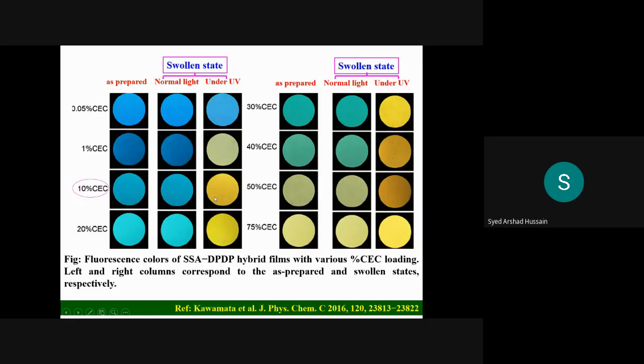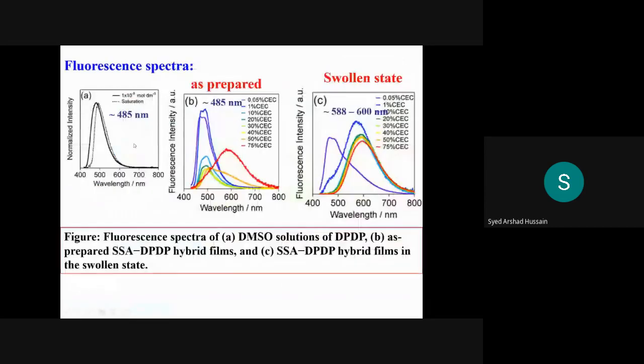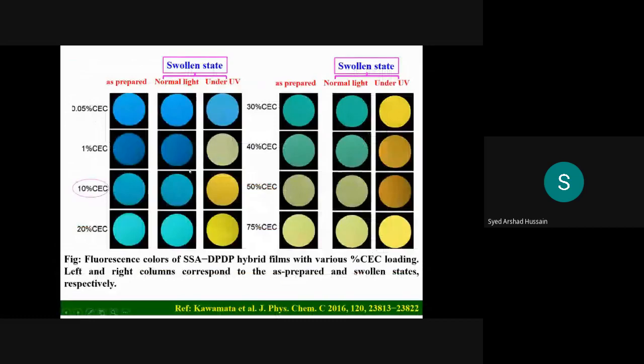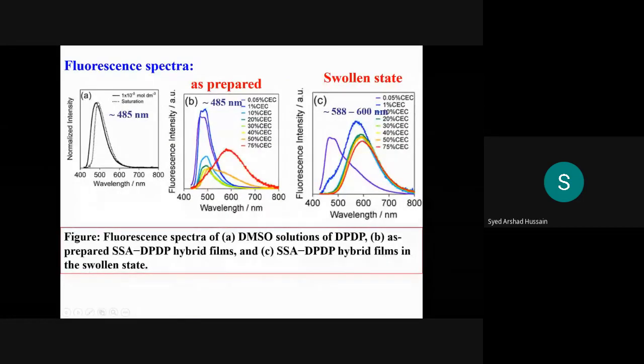So we analyzed why this color change happened. We did some spectroscopic studies, and these are absorption spectra. Before and after UV exposure, the spectra remain almost the same. But in the case of fluorescence, an interesting result was observed. Before UV exposure, you see the band lies at 485 nanometers, but after exposure, the band shifted to 600 nanometers and becomes very broad, situated at a longer wavelength than the original one. And these features are mainly the characteristics of an excimer.